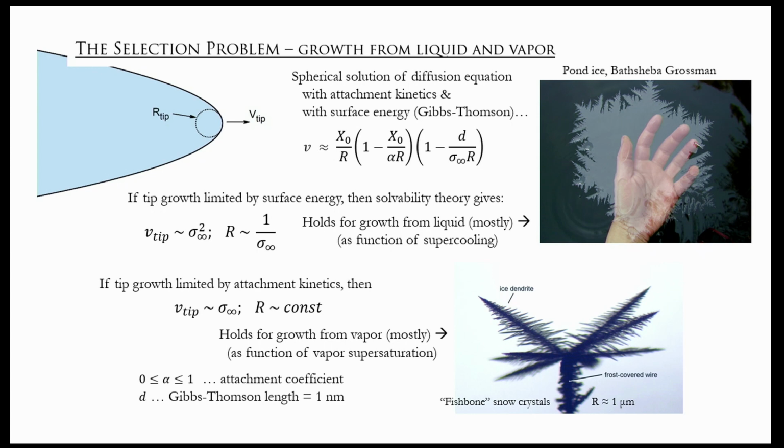But now we're going to do a Taylor expansion in alpha and d. d is the Gibbs-Thomson length. Okay, so if alpha is high and d is 0, no surface tension, then you just get the normal solution. But both these effects will reduce the velocity, okay? Because if alpha gets small, then this term gets big, and it starts to, this goes to 0, or gets smaller.